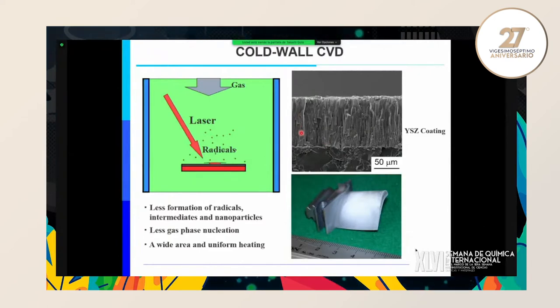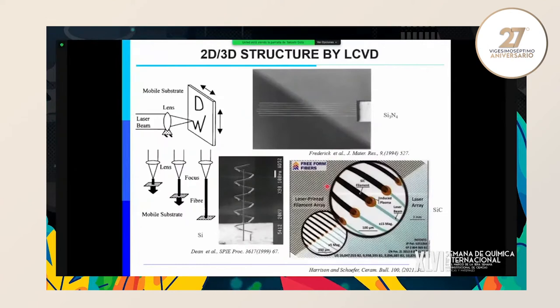So a much wider or more complicated shaped substrate, such as a gas turbine blade, can be coated, and the laser can be scanned, and yttrium stabilized zirconia film was coated by laser CVD. So laser CVD can make very thick, very complicated shapes, even using very reactive precursors like metal organic precursors. Actually, laser CVD was proposed almost 30 years ago. Laser CVD made wires of silicon nitride or silicon, and silicon carbide filament can be prepared by laser CVD.